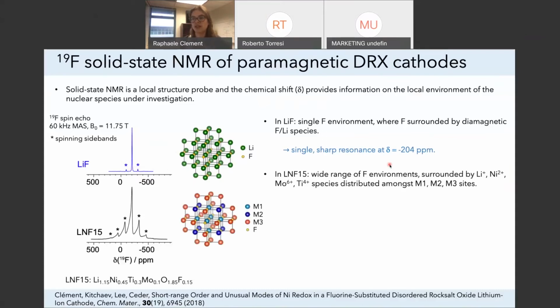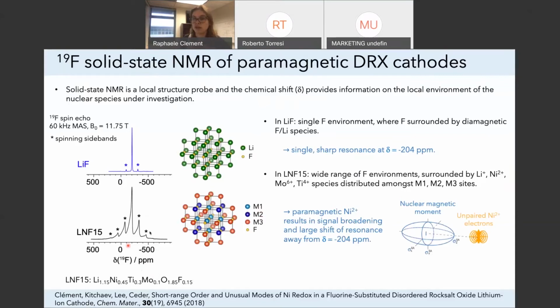But what we are really interested in here is understanding the local structure of our cathodes. And so this is a particular cathode, the composition is shown here. This is a DRX compound, a disordered rocksalt cathode. And in this particular material, you now have fluorine environments that have 3 coordination shells with different cation species, illustrated in light blue, in dark blue, and in red. So you've got these 3 coordination shells. And within these 3 coordination shells, your fluorine can be surrounded by lithium, but also by nickel, molybdenum, and titanium based on this composition here. So the number of local environments will be much larger in this material.